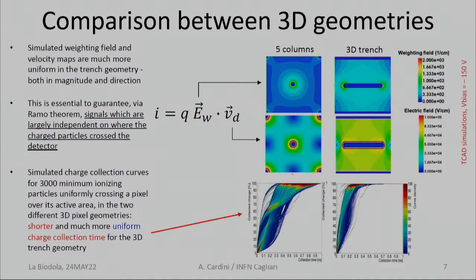Then part of it, it's not the weighting field that does it, it is the acceleration then, right? Well, the weighting field does one thing, but then you have to consider the electric field, the effect of the electric field on the velocity of the charge carrier. So you have both. The winning idea of those type of sensors is that the weighting field is uniform as much as possible, and the velocity operates, you have an electric field which is so high and everywhere that you operate in as much as possible saturated velocity. The consequence of this is that the shape of the signal